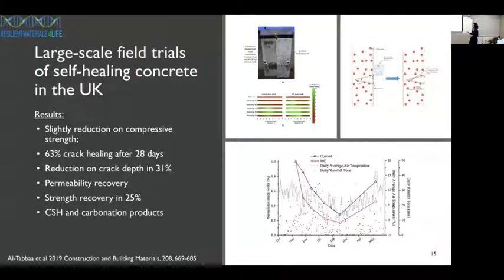permeability recovered by the same mechanism that I was discussing before, some strength recovery with the microcapsules, and CSH and carbonation products were observed being formed in the crack healing. This is the mechanism of healing that I was talking about before, but in addition to that,